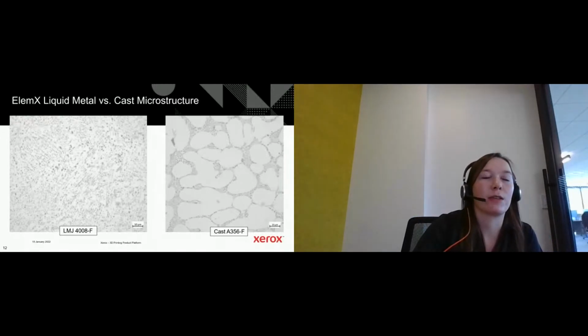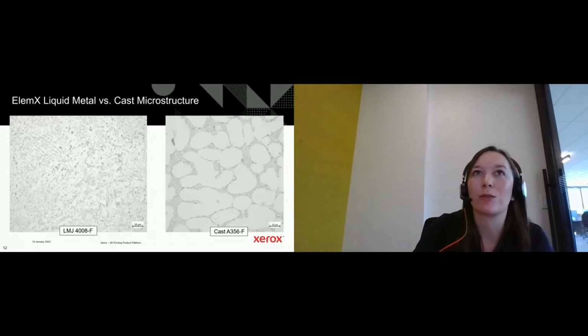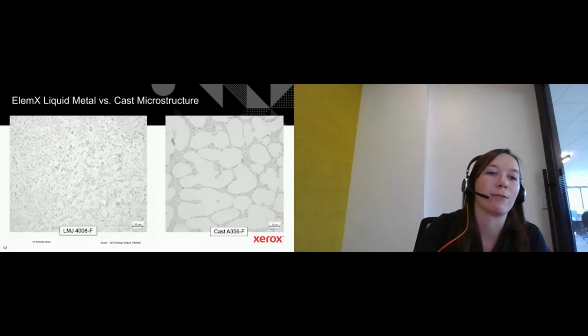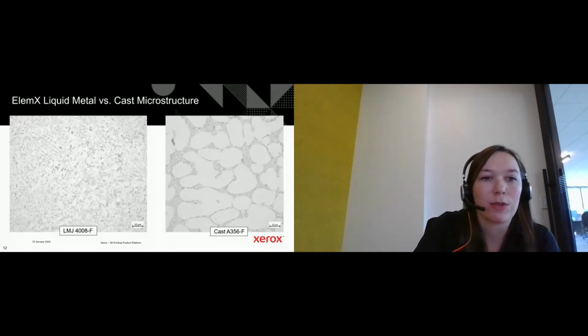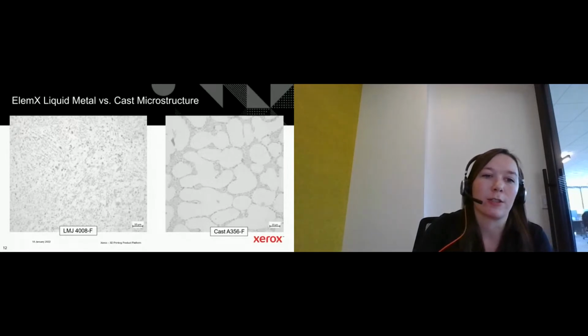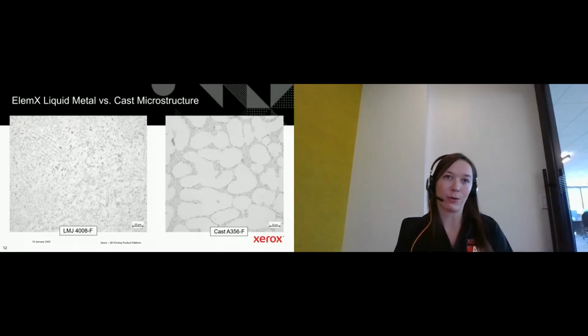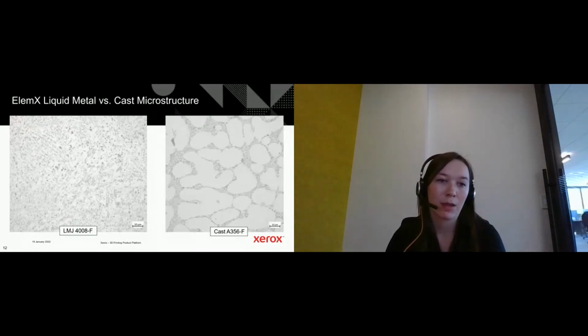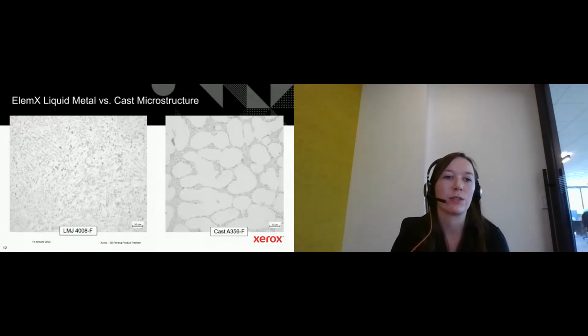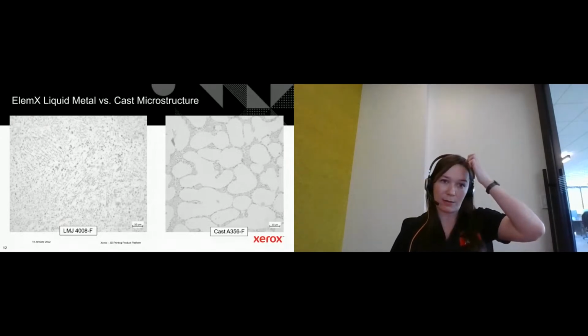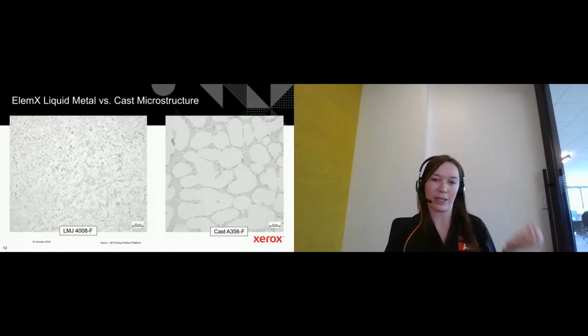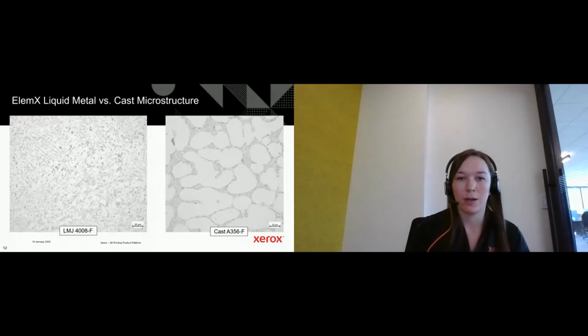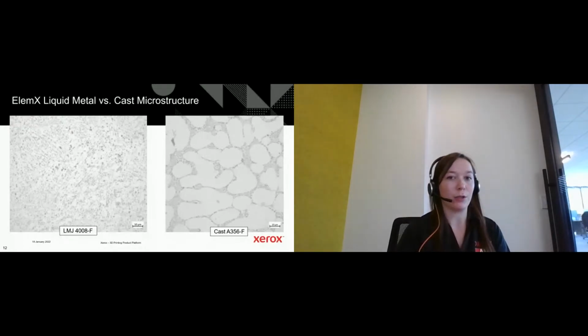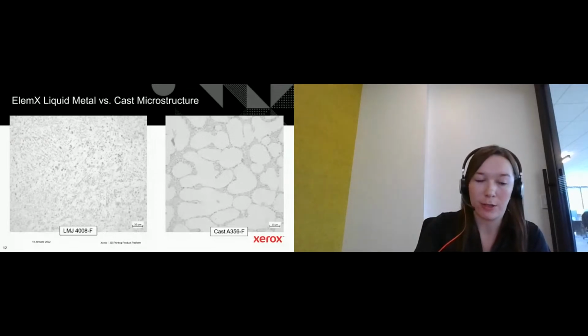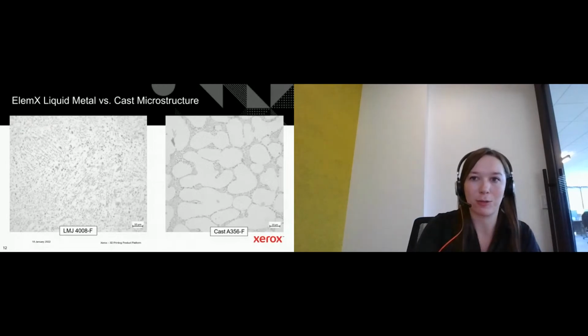With this 4008 aluminum, the primary strengthening mechanism is from the precipitation of silicon and magnesium. So these darker particles you see interspersed on either the casting or the printed part, those are the silicon particles. So you can see on the printed part, they're very evenly dispersed, whereas in the casting you end up with these sort of globs of the aluminum matrix. So the fact that it is so well dispersed kind of lends itself to some strength in our application.